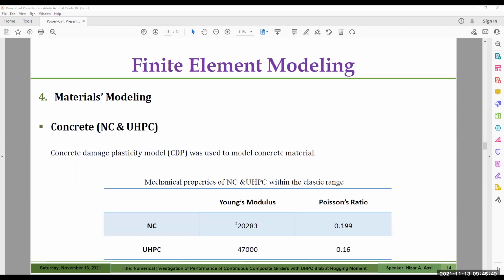For the material modeling, normal concrete and ultra high performance concrete were modeled using the concrete damaged plasticity model. For the elastic properties within the elastic range, this table shows Young's modulus and Poisson's ratio. As you see here, Young's modulus for ultra high performance concrete is double that of the normal concrete. So we expect that the behavior of the girders strengthened using this type of concrete will have higher stiffness within the elastic range, and this will be observed when discussing the results.